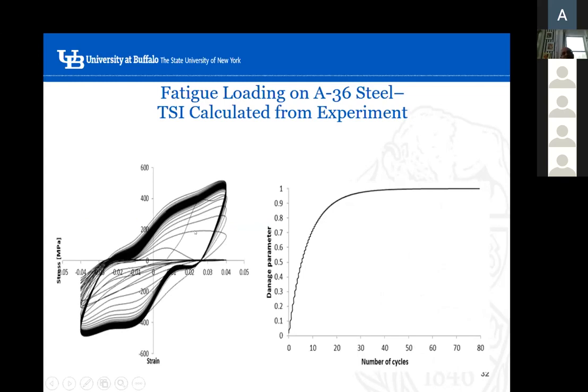Like, for example, if you take a simple bar, according to ASTM standards, and then test it under tension, compression, cyclic fatigue loading. And of course, you initially start here, and then as the material degrades, normally we define the slope of this stress strain diagram as the elastic modulus. As the material degrades, the elastic modulus degrades, and then finally it will break.